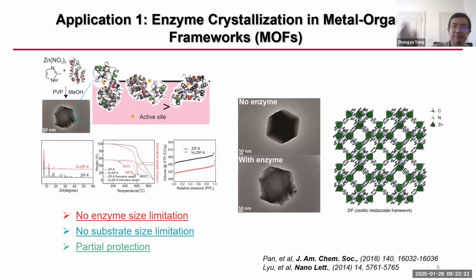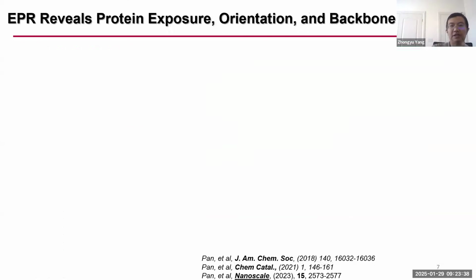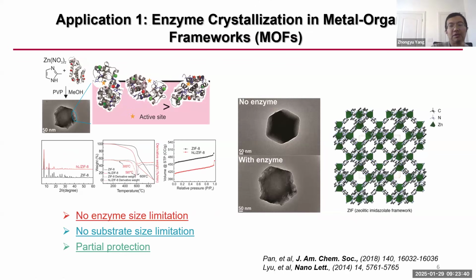We wash the co-crystals, and then the activity is still there. That means it's not because the enzyme is physically attached to the surface. It's got to be geometrically trapped on the surface. So you wash it, you don't lose the activity. And the next question is what's the orientation? Are all the enzymes oriented the same way, the same orientation, or are they random?